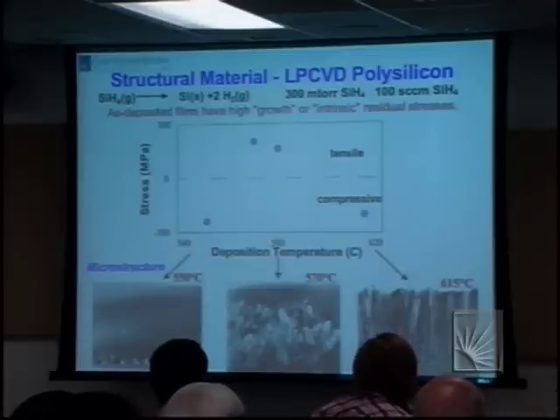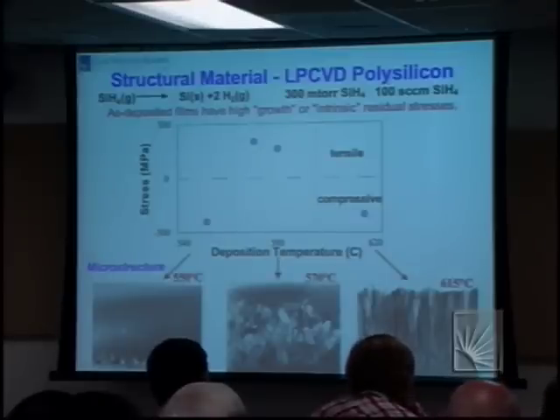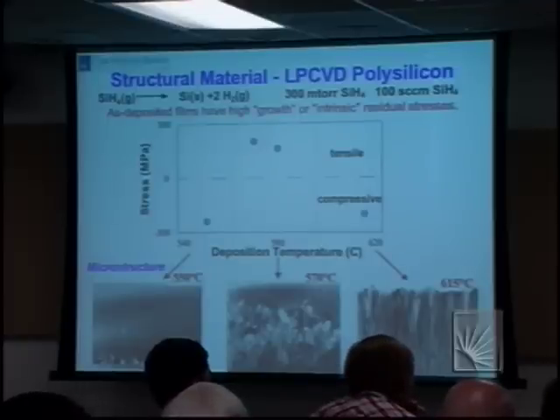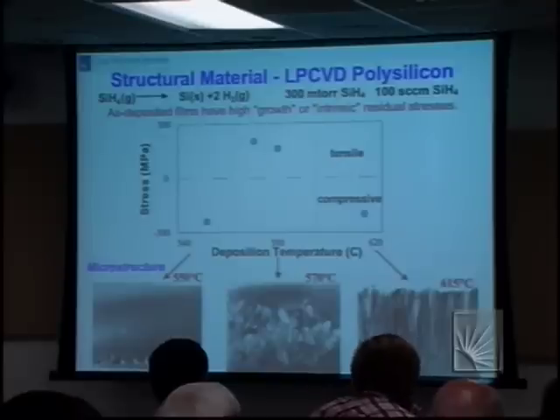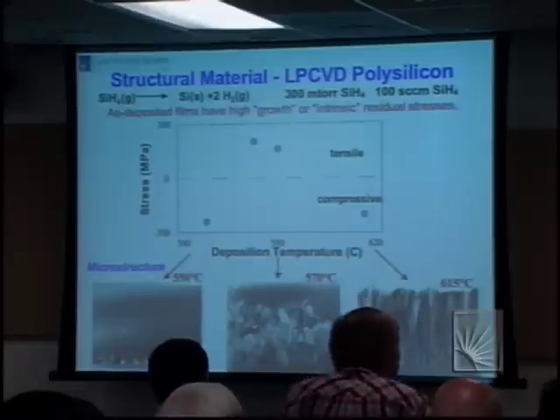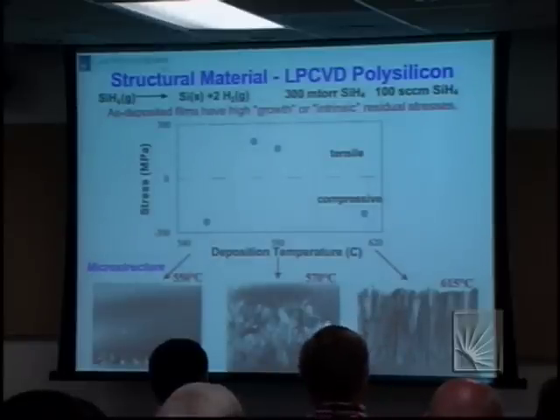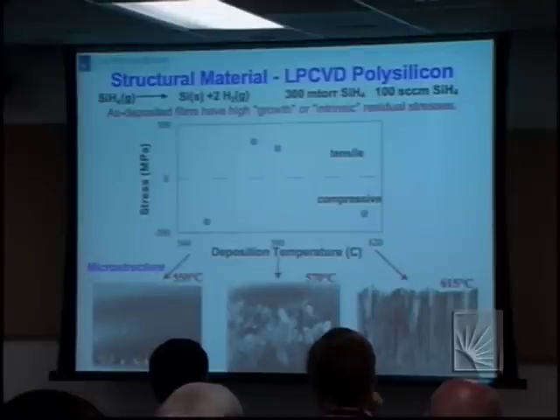At the lowest temperature regime, this is an electron micrograph. Each of these films is 5 microns in thickness, deposited at different times at these temperatures to give the same thickness. You can see it particularly clearly in this sample, this is the SiO2 sacrificial oxide on which the silicon is deposited. And the kinetics of deposition are just a tad faster than the kinetics of crystallization. I'll come back, it's an important point.